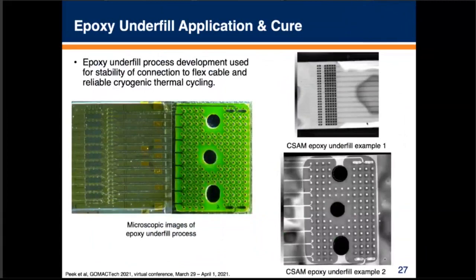Some more images here, specifically pointing out some of the underfill approaches. We've developed these approaches to be able to get the right amount of underfill inside of these structures, and get decent fill around the edges and in these densely bumped areas. That really helps stabilize things from a mechanical perspective.